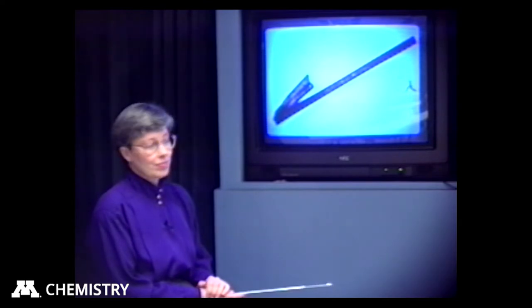And this is showing you again that crystal size, crystal quality, crystal width, crystal history has a lot to do with the initiation time at which a phase transformation begins or the rate at which it traverses the crystal. But then if we go back and take a picture maybe another week later, we find that the large crystal has finally transformed. But we don't know how to control that transformation. We don't know what initiates it and why it took place at a different time than the smaller crystals.